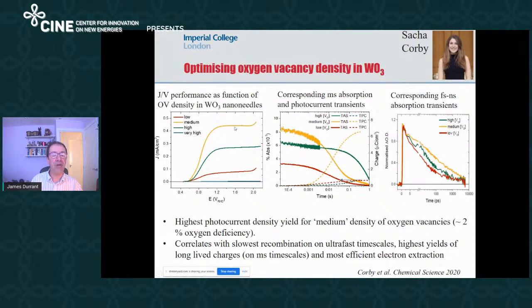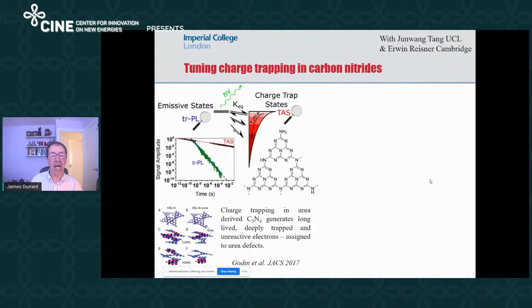And so the yellow curve here corresponds to an intermediate oxygen vacancy density compared to the two extremes. And we can see that directly in the kinetics, that we get more efficient charge extraction, and indeed longer lived carriers in the presence of a medium concentration of oxygen vacancies. And that's just one illustration of how defects aren't always a bad thing in some of these materials. As another example, here's carbon nitride.